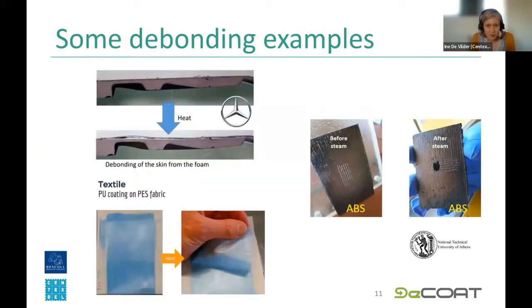I just have here some examples. For example, here we have a PU foam with a PVC foil laminated on top. By using a triggerable primer layer and after exposure to heat, this PVC film can be nicely removed. Another example is one on textiles. We have a PU coating on polyester. The blue is just for visibility. And here, after the heat triggering, we can also nicely remove the coating from the textile. And here is one example on ABS, where we apply a steam treatment to induce the removal of the paint. As you can see here, we have a good adhesion before, and after it can be removed.